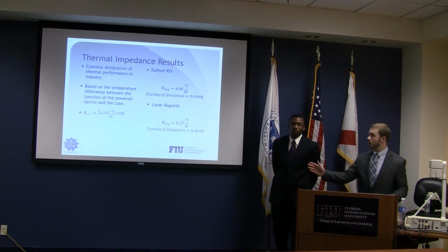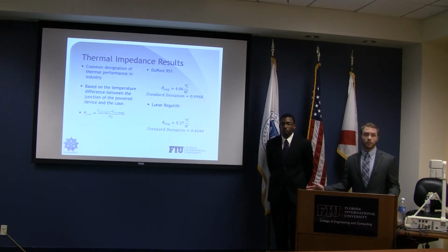And then we took and averaged those temperatures on the backside of the board and used the equation based on the MIL standard, which you'll see right here, which is the difference between the junction reference, which is the embedded thermocouple, and the average case temperature, which are the 40 points averaged. This is per unit of power, or watt.